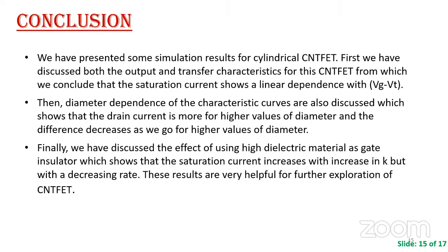So in conclusion, we have presented some simulation results for cylindrical CNT FET, and we conclude that the saturation current shows a linear dependency with Vg minus Vt, that is the overdrive voltage. Then we discussed the diameter dependencies of the characteristic curves, which show that the drain current is more for higher values of diameter, and the difference decreases as we go to higher values of diameter. Finally, we have discussed the effect of using high dielectric material as gate insulator, which shows that the saturation current increases with increase in K, but with a decreasing rate. These are very helpful for further exploration of CNT FETs.